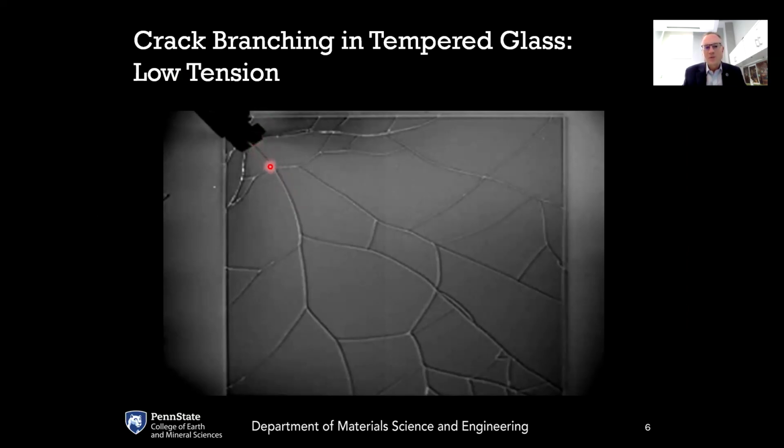When it gets to that point, the crack cannot propagate any faster, and so it has to branch. It has to bifurcate or sometimes even trifurcate. So it's branching into two or sometimes even three new cracks so as to be able to release that tensile energy at a faster rate. When those new cracks form, each one of them is then going to propagate and accelerate as its tensile energy is being released until that new crack reaches its terminal velocity.